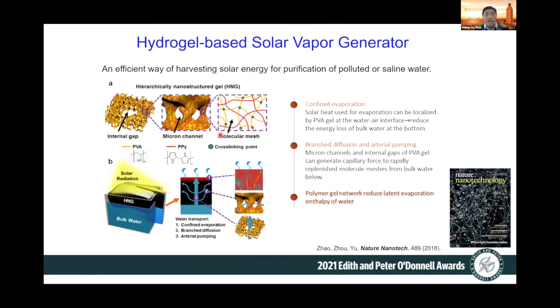They can offer highly tunable water-polymer interaction to effectively reduce the energy needed for water evaporation, basically changing the latent heat of water evaporation. In our first work demonstration, we utilized these hybrid gels. One is a hydrophilic polyvinyl alcohol gel, which serves as the hydrophilic polymer network. And polypyrrole is a semiconducting polymer, so it can effectively absorb sunlight and locally heat up the molecular mesh. And due to the reduced energy needed for water evaporation, they can achieve very promising